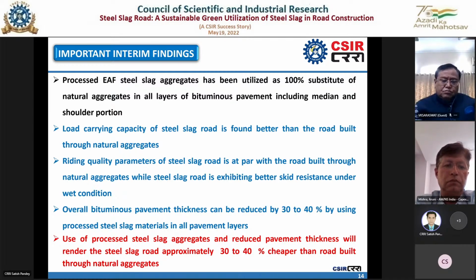Load carrying capacity of steel slag road is found far better than the road built through natural aggregate. Even when we applied the load up to 140 kilonewton, which is far higher than the specified limit in the Indian Roads Congress guideline, at 140 kilonewton load also the measured deflection is comparatively lesser than the deflection measured in the road segment built through natural aggregate.